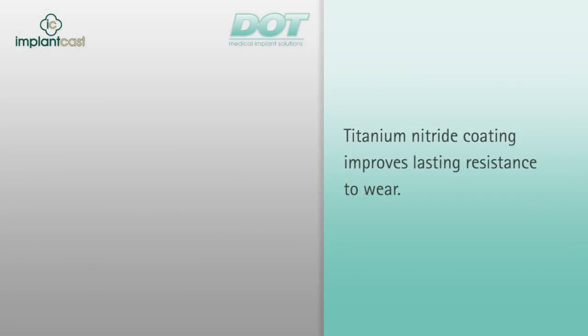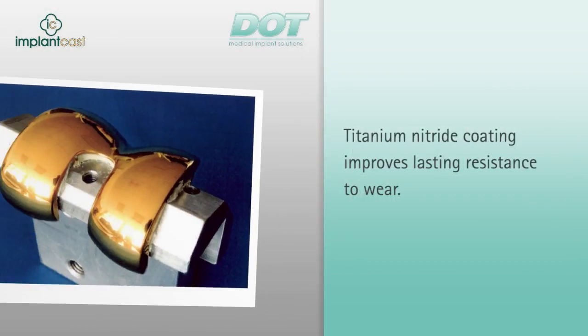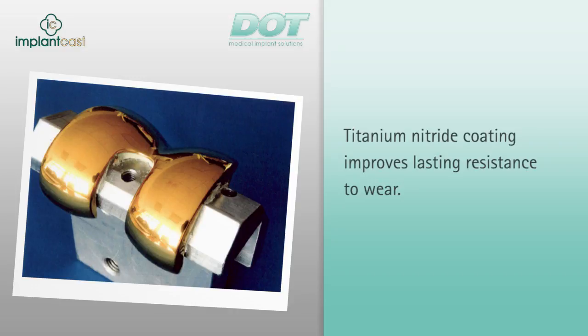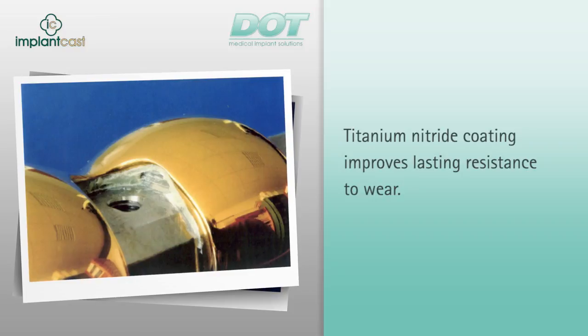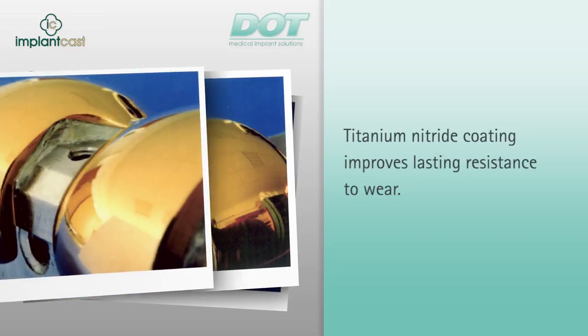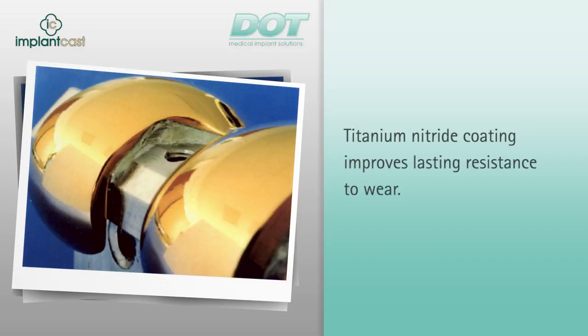As evidence of the resistance to wear, titanium nitride-coated knee joint prostheses were examined in a simulation in which the components were subjected to 1 × 10⁷ load cycles. Next, the surface of the contact zone was analyzed. During the entire trial, no extensive change to the coated surface was found. No chipping or rubbing off of the layer occurred.